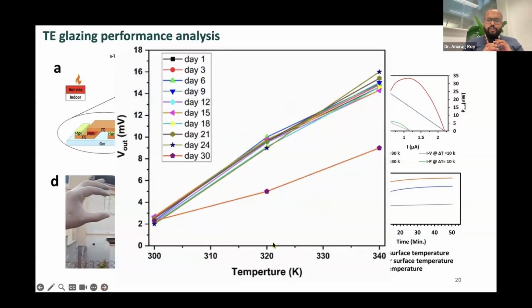And we tested for 30 consecutive days to see if there were any changes. But yes, after 30 days, we have seen a power drop. There's a voltage drop actually. It was initially showing some 16 millivolt voltage, but then it dropped to almost 7 or 8, almost half, because of material degradation.